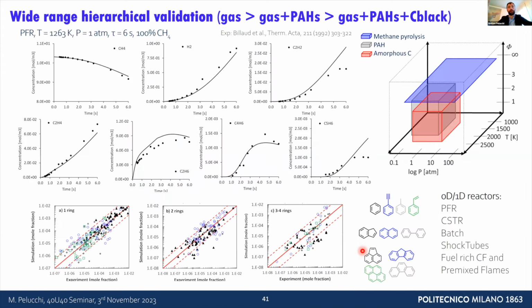Of course, if we think about turquoise hydrogen production, we have gas phase reactivity, we have soot formation, we have deposition on the walls. So we need to validate this gradually. We need to look at the gas phase while taking into account PAHs and soot formation. We need to look at PAH formation, taking into account soot formation and deposition phenomena. And then we can look at the deposition phenomena once we have everything else validated.